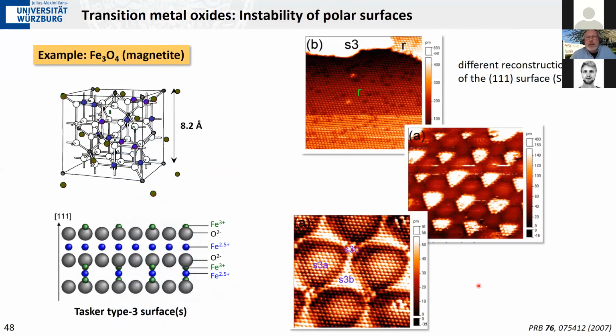Here's one example where I would like to discuss this briefly. This is magnetite again, which is a system where wherever you cut a surface, you always have a type 3 polar surface. As a consequence of that, you get all kinds of different metastable surface reconstructions. This is an STM study that we have done a while ago on such surfaces, and you find all kinds of different reconstructions. It's very weird, with large periodicities,